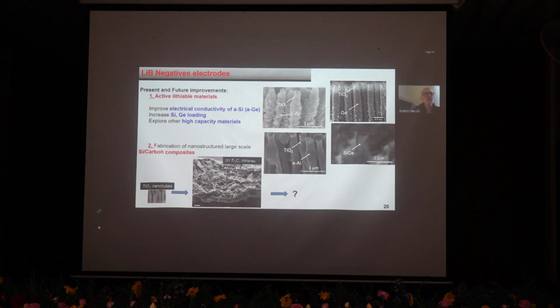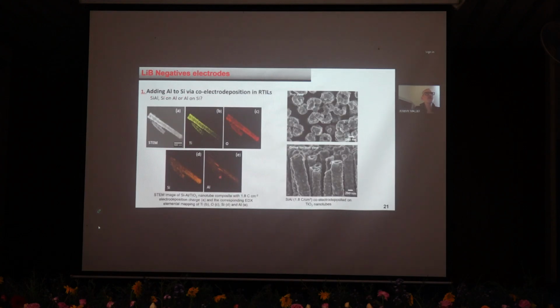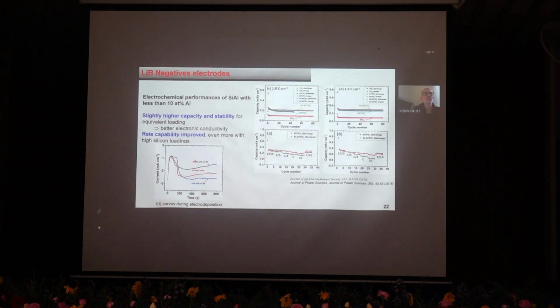And then also, to increase the amount of silicon, we try to change the template. Instead of using TiO2, for instance, we are working right now on the Ti3C2 MXene template. Just a few last results. So that is aluminum-silicon. We have this showing that we can grow silicon aluminum on top of TiO2. The amount of aluminum can be controlled by the electrochemical parameters, so we can control the aluminum content inside the silicon, and this low amount of aluminum is enough to improve the electric conductivity.